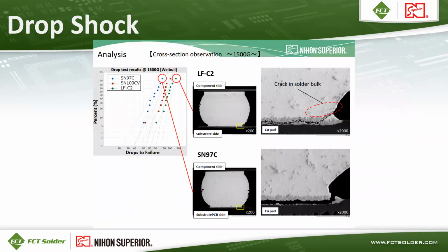So here's some cross sections of those failures. LFC2 is shown at the top. The crack in that case is running through the bulk of the solder. Below that, you see a cross section of SAC 305, which has a crack through the intermetallic compound there. You can see the intermetallic cracked pretty completely.